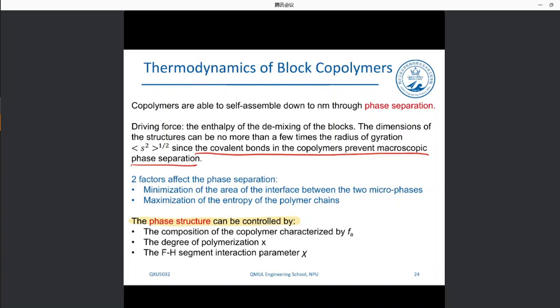And we have three parameters that affect the phase structure. How do we control it? Firstly, as we discussed already, is the composition of the copolymer. By controlling the composition of the copolymer, we know that we induce a certain phase structure based on the percentages that we saw already. The degree of polymerization is also something that allows us to control how much we have one monomer growing within the main chain of the polymer, that is N, okay, because both these two parameters look the same. This is pronounced chi, and also we have the Flory-Huggins interaction parameter chi, that is Greek chi.